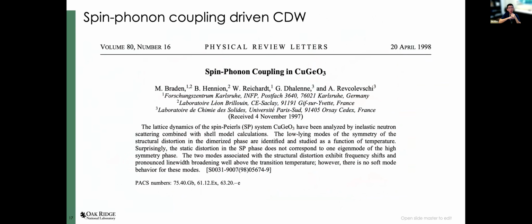Once we see the spin-phonon coupling, if you really go deep in the literature, it's actually not the first time it's been seen. In spin-Peierls systems, people have been talking about this for decades. Here, just to show an experimental paper back in 1998, where people saw a spin-phonon coupling effect in spin-Peierls systems. Similar to our observation, instead of a phonon softening effect, they actually observed quite a strong phonon hardening effect that is consistent with our observations. But whether there's a more fundamental relation between these similarities probably needs further theoretical studies.